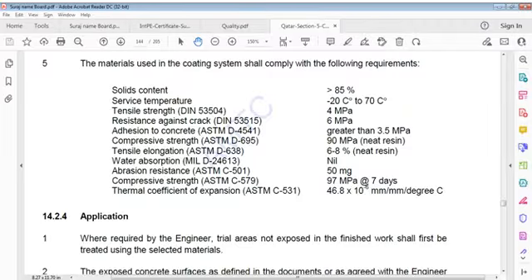Tensile strength, that is DIN 53504, 4 MPa. Resistance against crack, DIN 53515, 6 MPa. Adhesion to concrete, that is ASTM D 4541, greater than 3.5 MPa.